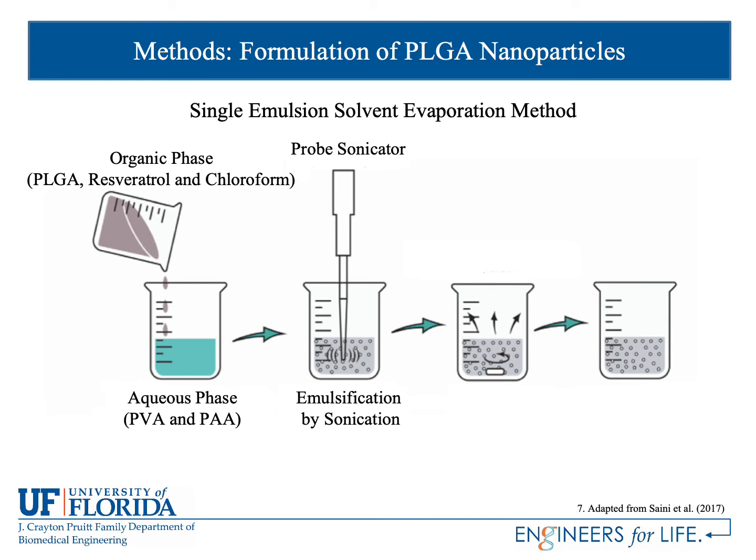Next is the emulsification by sonication. The organic phase is going to be mixed with the aqueous phase to form an oil-water type of emulsion. The probe sonicator produces sound waves that vibrate the particles and can lead to further mixing.